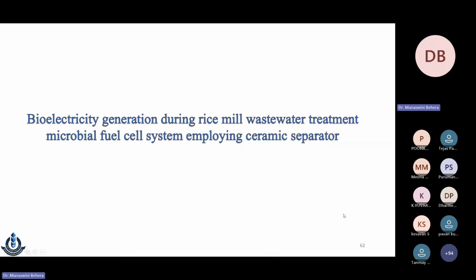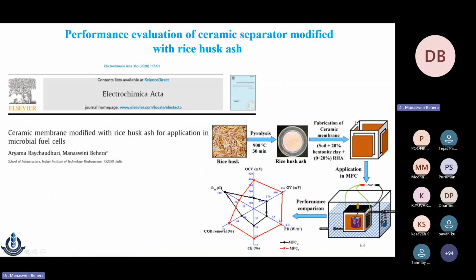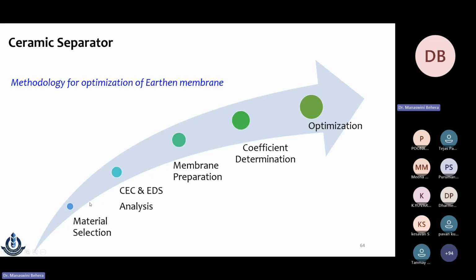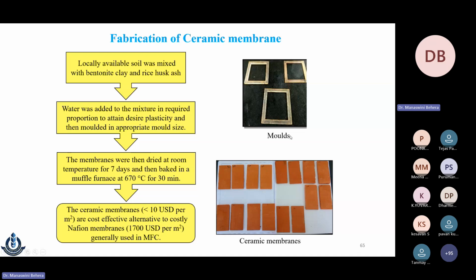Okay, so until now we were using domestic wastewater. We could also treat rice mill wastewater, which is very highly polluted, in this fuel cell system. Here we optimized our membrane preparation. Earlier, we prepared this membrane using bentonite clay and locally available soil in some proportion. Then we mimicked the pottery making method, like making a plastic solution, and kept it in a mold. Then we air dried it, and burnt it in a muffle furnace at a particular temperature to prepare the membrane. To increase its cation exchange capacity, we added rice husk to increase the porosity and give better proton transfer.